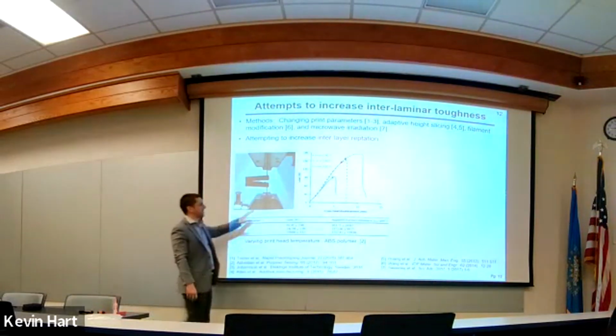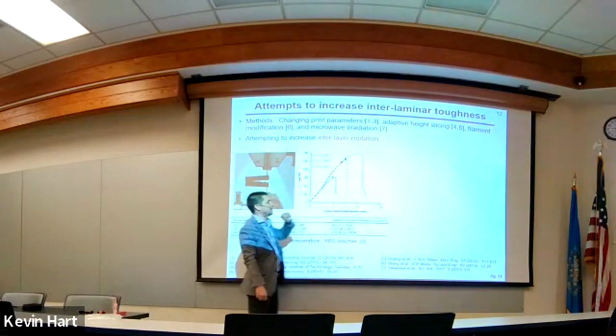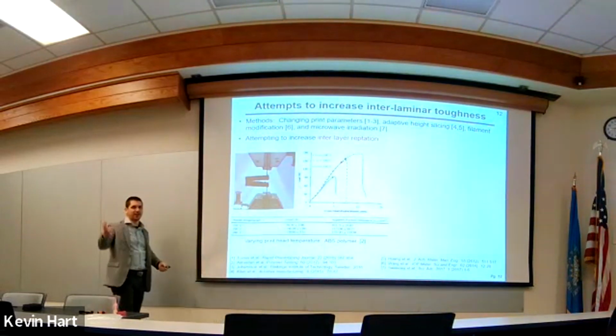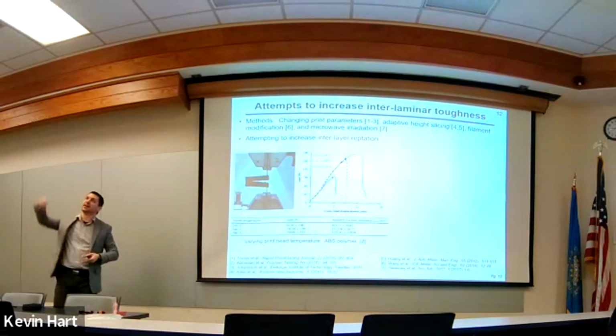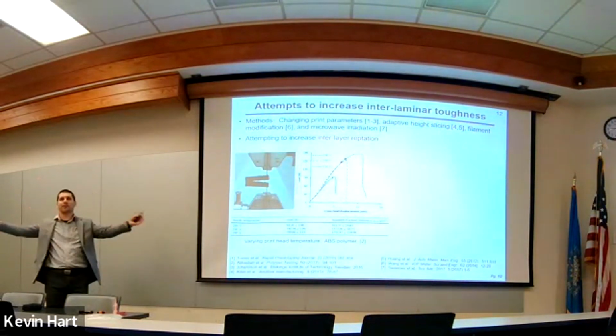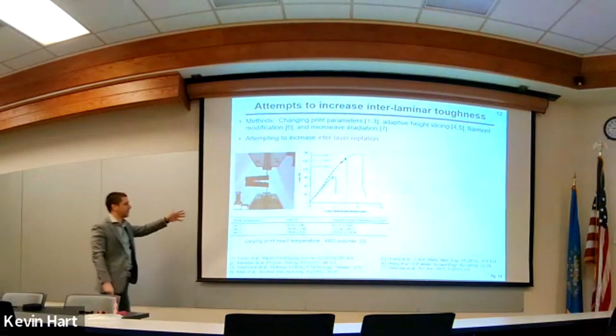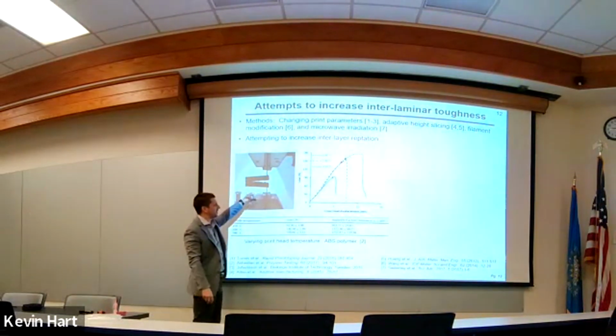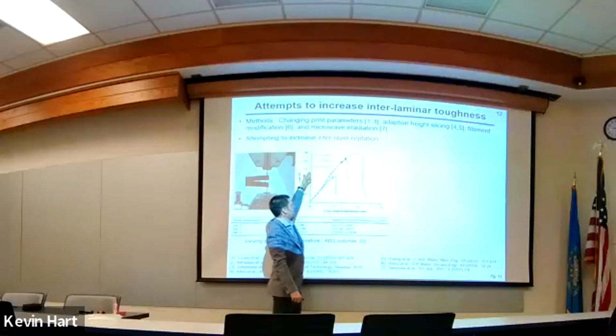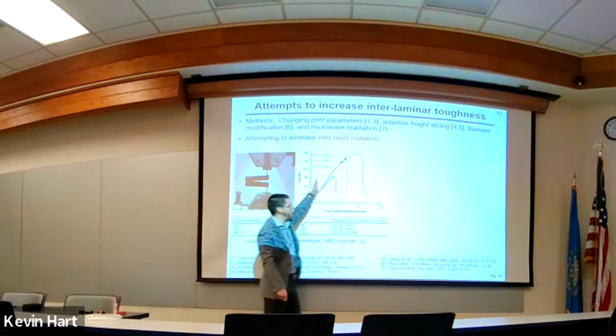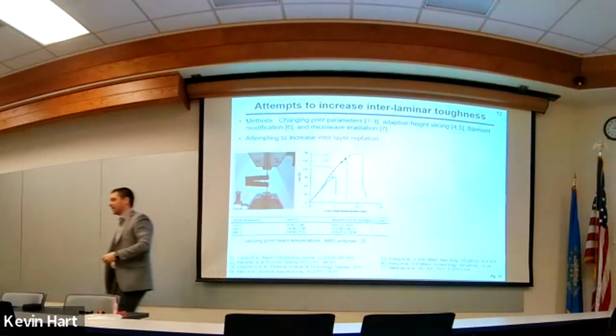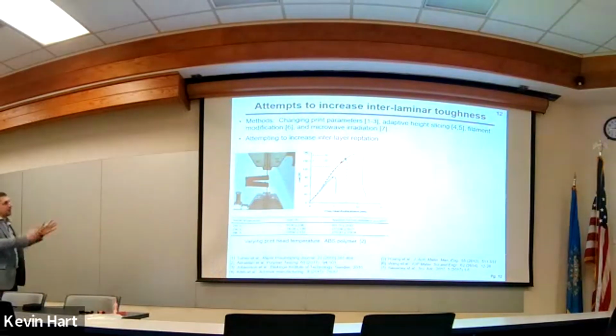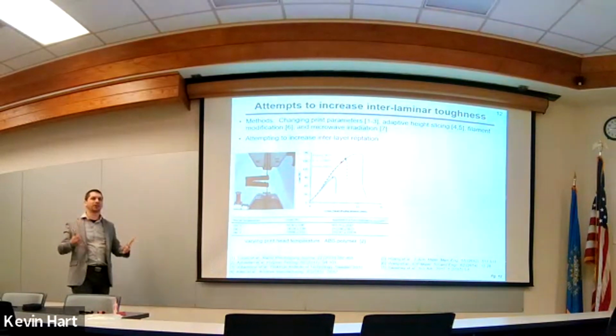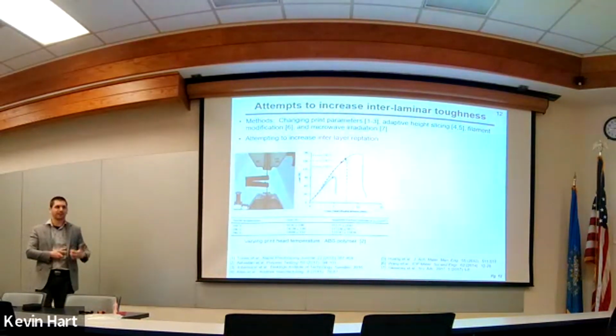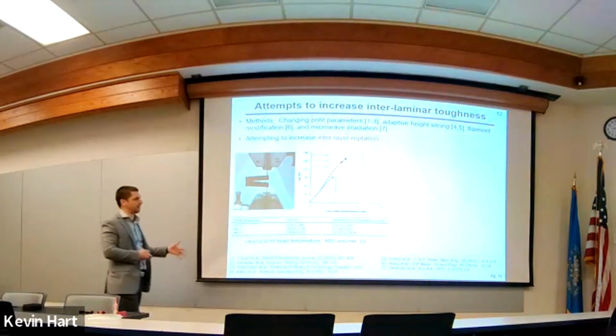One thing that you might want to try is changing the temperature of the nozzle during the 3D printing process. When you're 3D printing an object, you can control the nozzle temperature. For those of you that haven't 3D printed, a higher temperature might give you more flow of your polymer and create a better bond. And that's what these people showed. They made what are called compact tension specimens, out of PLA. When they printed using increasing nozzle temperature, they found increasing toughness. So a larger area under the curve for the same crack opening gives you more toughness for your sample. That's one nifty way to do it. But their results didn't get anywhere near the injection molded strength that you would want out of a really good engineering material. So that's one way that it can be done.